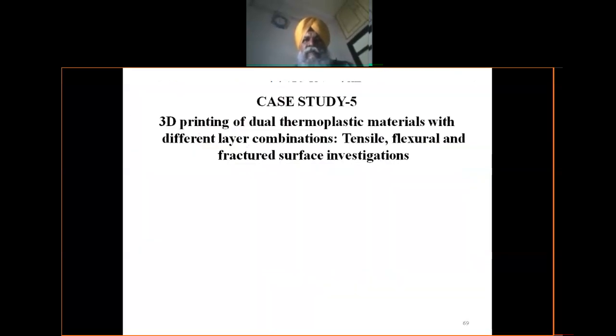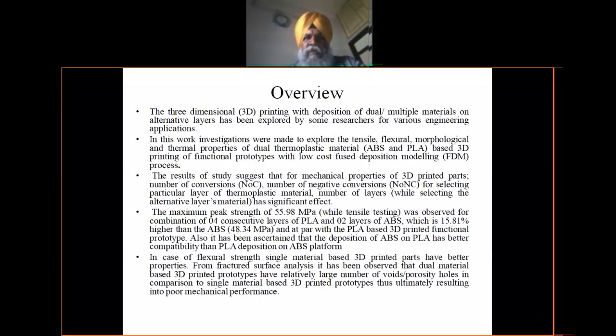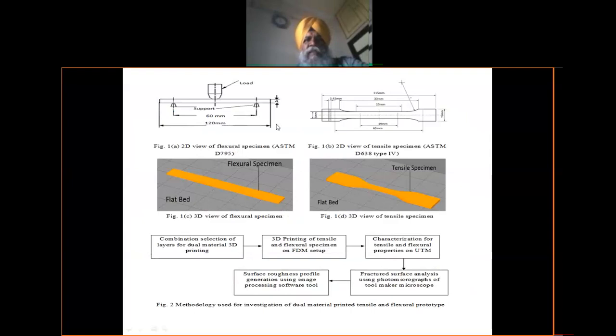Now the last discussion before I conclude my talk is how I will decide which dual material I am going to print in the different layer combinations. So this case study is on this application. For this case study, we selected two different materials. One is ABS and another was PLA, and both were 3D printed. This is the standard specimen as per ASTM D795 for flexural testing. Similarly, ASTM D638 for tensile testing. You can see some printing is going on.